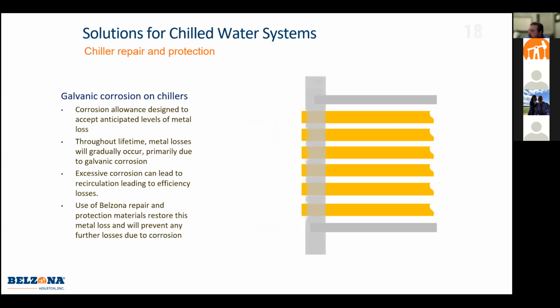So this is just a little animation showing there's your allowed corrosion. Now it's getting a little too far past the allowance. That's when, especially your roller expanded tubes, they start to leak between the tubes and tube sheets, giving you some efficiency loss and can also be a little dangerous. So we can come in, blast these, fill these back in flush with a paste, and then put a good 2-coat system of our ceramic epoxy.